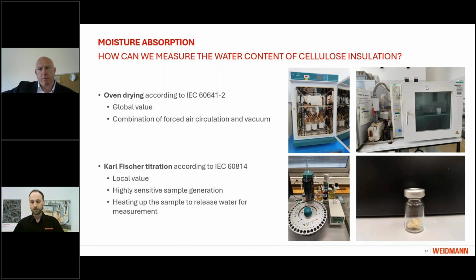If you want to do this, for example, you want to know the humidity of the different layers of laminated board, then you need to use coulometric titration. Here we can take a very small amount of material and test that, and then we know exactly the water content at that specific location. However, when you want to use this method for a global value, you really need to take samples at many locations and then use statistics.